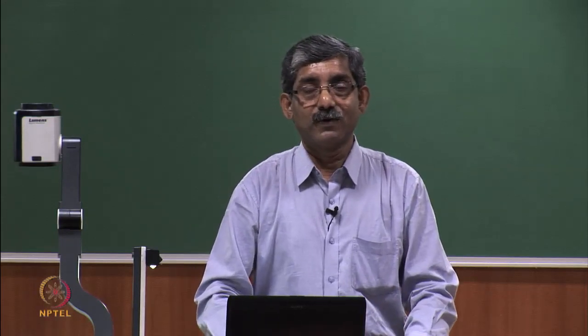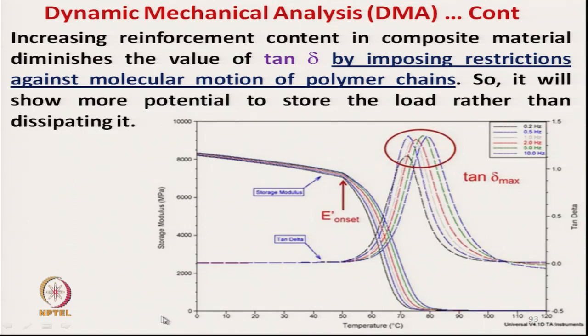This diagram shows the temperature increasing on the x axis, and the y axis is the storage modulus. Increasing the reinforcement content in the composite material diminishes the value of tan delta by imposing a restriction against molecular motion of the polymer chain. That means, if we incorporate reinforcing material, the composite will become more elastic. So, it will reduce the tan delta value.